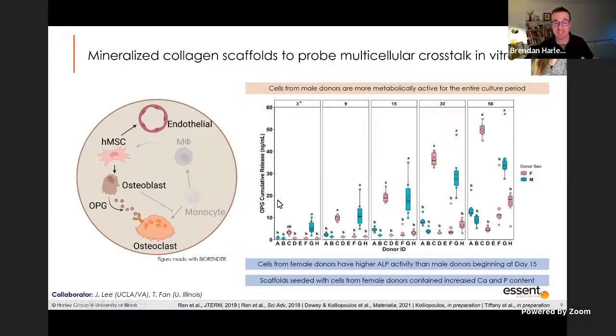So this is a plot here looking at secretion of that osteoprotegerin factor that's known to inhibit osteoclast activity and was really important for our bone to functionally regrow. And here again, we see some sex-based differences where a number of female donors were producing much more osteoprotegerin. And in fact, we saw cells from female donors had higher ALP activity, which is an early marker of new bone formation, and that scaffolds seeded with cells from female donors had much more calcium and phosphate crystal mineral deposited in the scaffolds over time, suggesting that there might be some important sex-based differences in how cells from different patients would respond in our materials. And so that's an avenue we're exploring now to understand how can we create versions of our material for older patients or younger patients or patients with underlying diseases such as diabetes to support maximal bone growth.